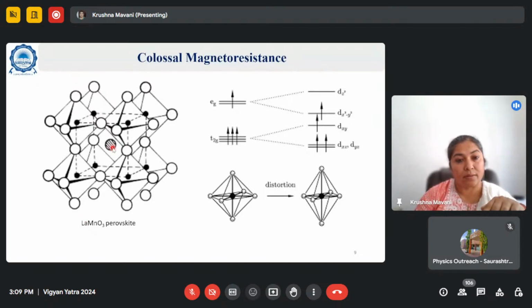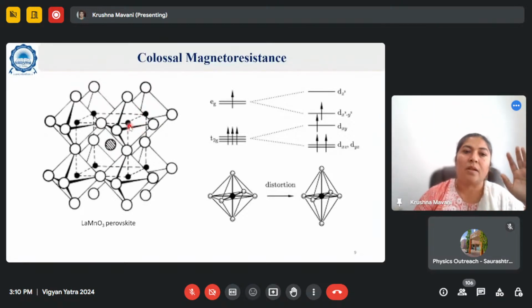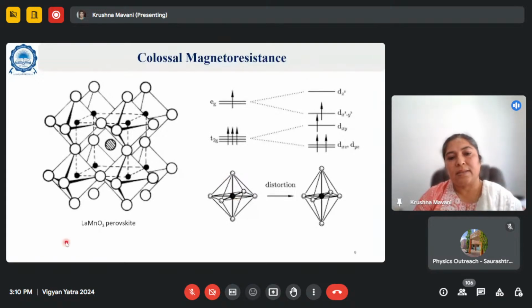La is 1 here. Manganese, because of sharing, actual contribution is 1. So La, Mn and oxygen contribution, if you count with sharing and all, finally it will be O3. So if I see just one octahedral, it is called MnO6 octahedral, just taking one manganese in the center and 6 oxygen ions here. So this is the ideal structure. Now manganese in this case, lanthanum is a trivalent ion, manganese also a trivalent ion.